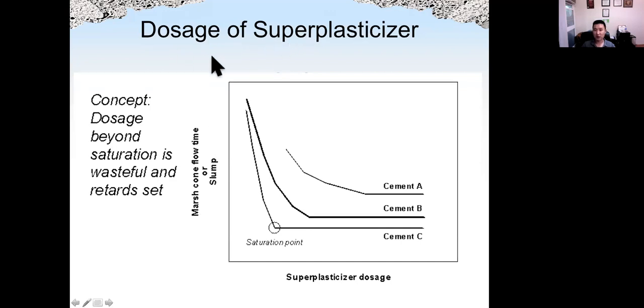Here we talk about the dosage of superplasticizer. This shows different types of cement. If we increase the dosage and measure the flow of the cement paste, what we can see is that as we increase the dosage initially, the flow time will be lower, which means the slump becomes higher.